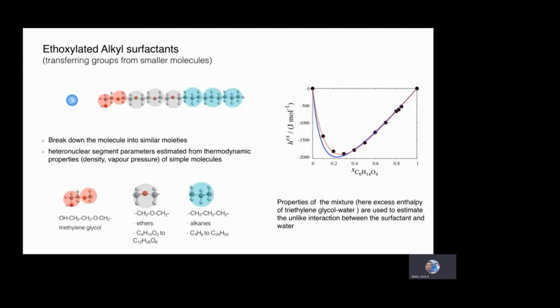The central ether groups, we fitted to the different available ethers in the experimental data available. And the end group, which is basically a glycol group, we fitted to the properties of triethylene glycol. And what we did was assume, and here's a leap of faith, that by joining these groups, the resulting molecule would have the correct behavior.